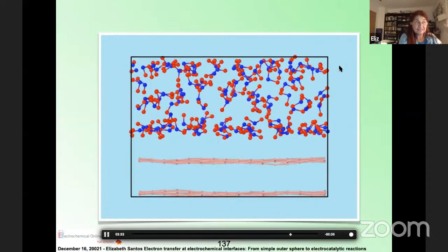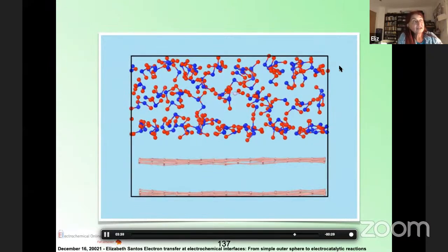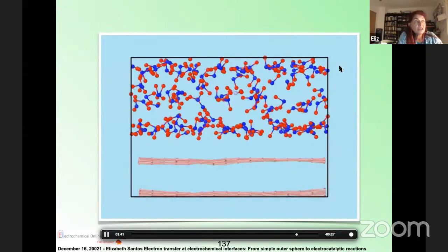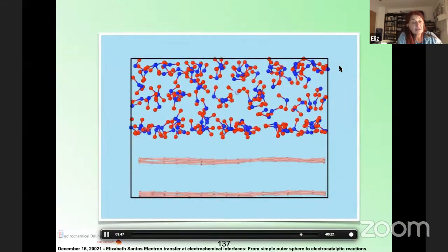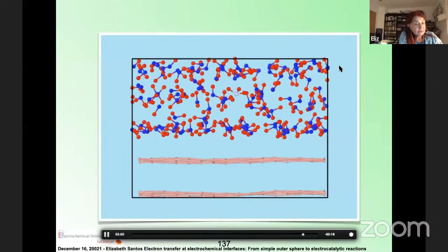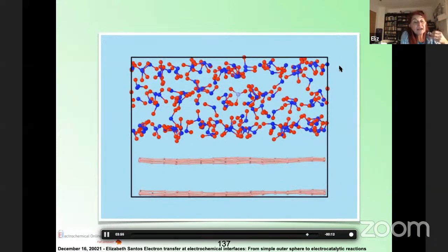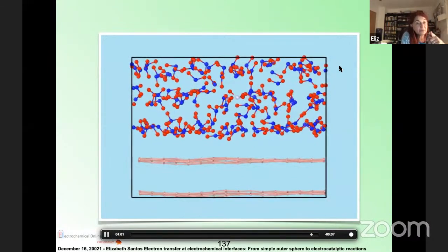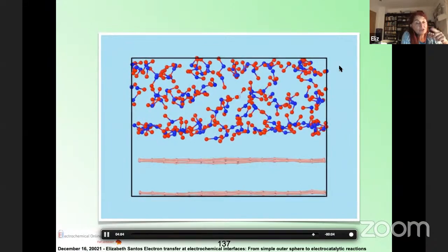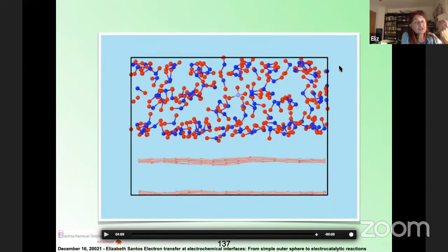That is the plan, but at the moment these are only approximations, and obviously if we have a charged species, the interaction should also be different. With DFT, we have calculated only the interaction of the neutral hydrogen when it is coming to the surface, and then it becomes charged when we move this electronic position due to the solvent interaction. But we assume that the interaction is the same. But this is an approximation.